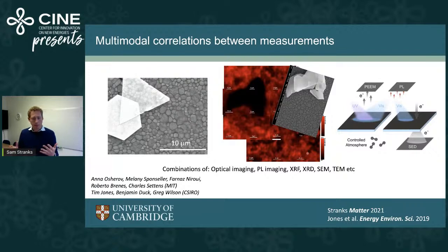What I'm going to show now are various microscopy measurements on the same scan area. Here we want to take a region of a film or a device, measure its optical properties, and then perhaps look in the electron microscope and measure its structural or morphological properties. To do this, we need very good fiducial markers, so that we can image register and precisely compare these images between different measurements. What we typically use are gold fiducial marker particles. These are nanoscale, at least in thickness, and microns in lateral dimension, and they cluster into these unique shapes. They give very good image registration, and they're very unique, so we can find them on the sample again.